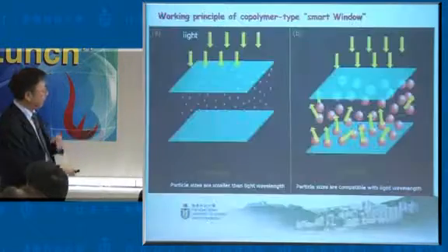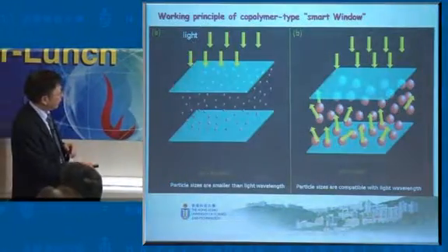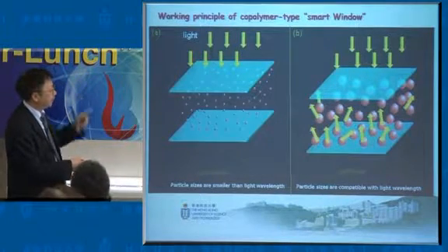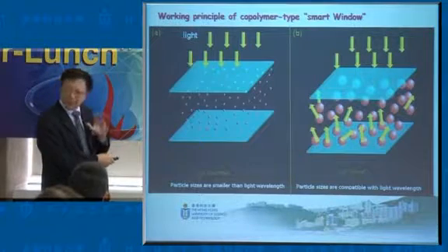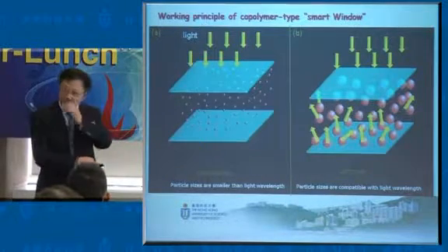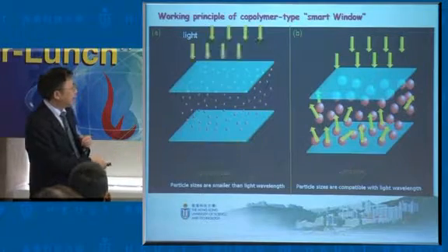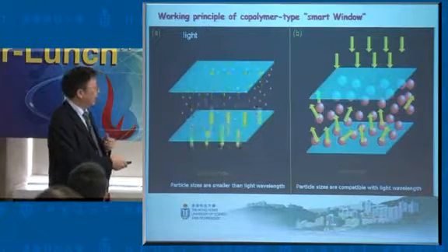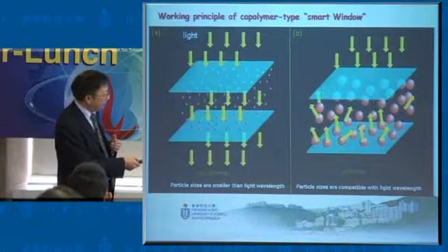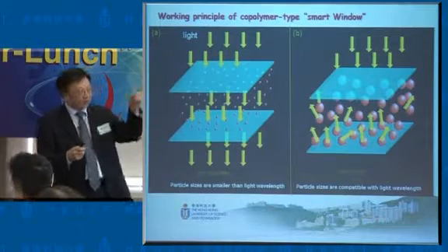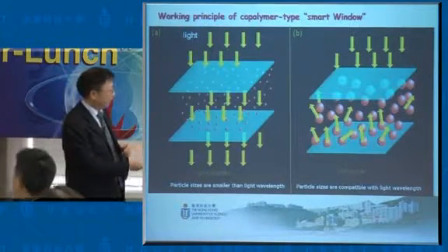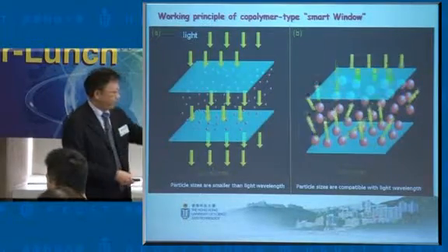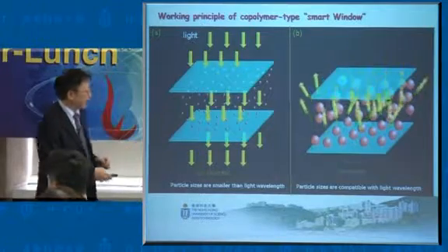So from here I'll give you examples. Here's a container inside with some small polymers. At low temperature, it has small particles, so the beam can pass through. We call it transparency. However, if the particle is big enough, comparable to the light wavelength, you can see some scattering, so the light is broadened. Let me show you later how it works in our demos here.